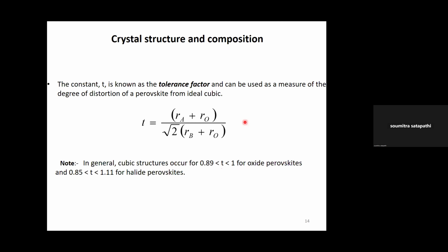Hybrid halide perovskites. Now, for hybrid halide perovskite, there is a formula. This formula takes the atomic radius of the consisting atoms which make your perovskites. For example, the tolerance factor T is defined as the radius of the A cation in the ABX3 or ABO3, plus RO for an oxide perovskite, it will be RX for a halide perovskite, divided by square root of 2 times RB plus RO. Now if the value of T is between 0.89 to 1, then you call it an oxide perovskite. And if it is 0.85 to 1.11, then it is halide perovskites.